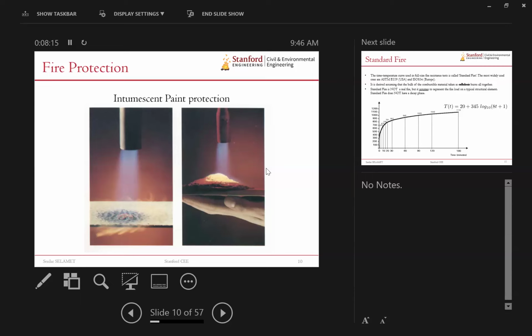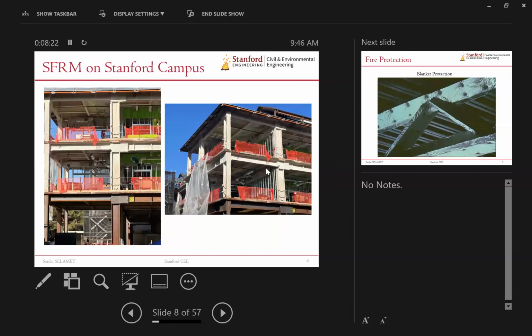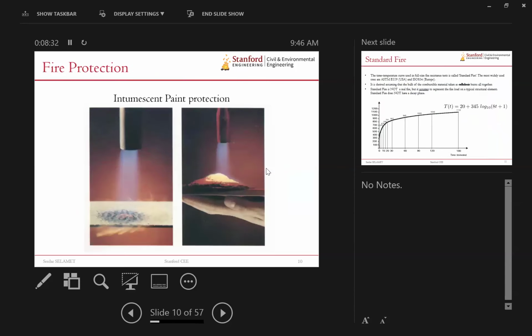And it looks aesthetically pleasing because it's just paint. It could be any color. So imagine that you would be applying intumescent paint on this bare steel, and you can keep this color and it will just look good, or you can just change the color. But it is expensive, and it doesn't protect at very high temperatures. For example, if you have temperatures reaching up to 900 degrees, it actually starts to fall off. So it's not sustainable for a long time if you have severe fires.